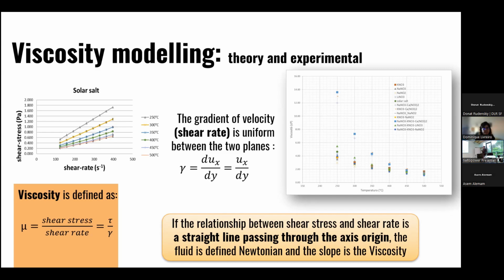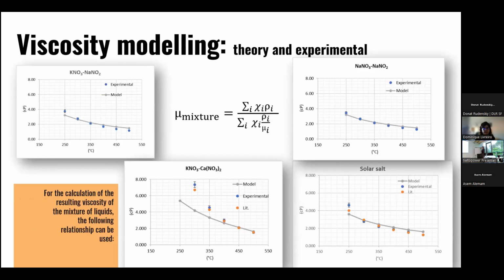And for the nitrate salts, if the relationship between the shear stress and shear rate is a straight line that passes through the axis origin, this fluid can be defined as Newtonian, and the slope of this curve is the viscosity. So once we performed all the experimental tests, we tried to simulate, to model the viscosity of unknown mixtures using this formula. And I reported only some results.